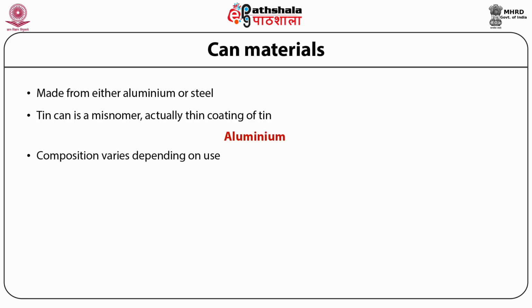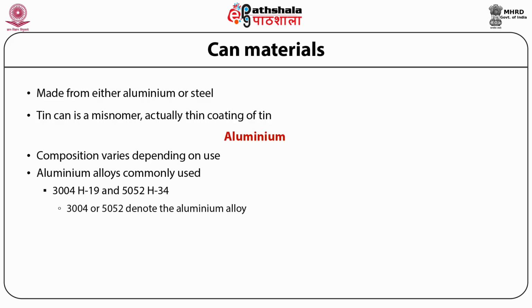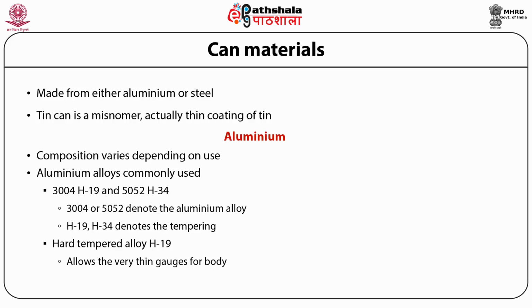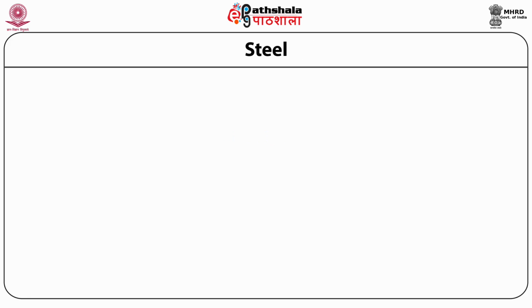The composition of aluminium alloys for rigid containers varies according to the intended use, with up to 5% magnesium, 1.5% manganese, and traces of iron, silicon, zinc, copper, and titanium. Aluminium alloys or tempers commonly used are a fully hard material such as 3004 H19 and a softer one such as 5052 H34, where 3004 or 5052 denote the aluminium alloy sheet and H19, H34 denote the type of temper. The hard tempered alloy H19 allows a very thin gauge which makes the container bodies economical, and shallow drawn parts such as can ends use alloys with less ductility and medium temper of H34 for average conditions. Next material used is steel.